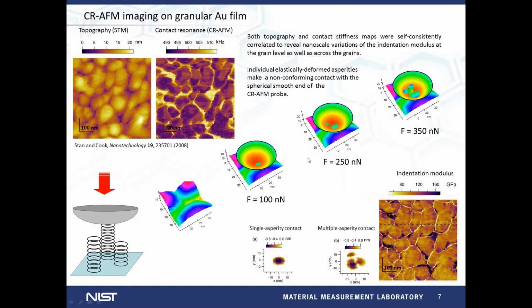An example of more complicated contact geometry is shown here on a granular gold film, and in this case, during scanning, the tip sample contact experienced significant changes in terms of contact area size and number of contacts. The contact is in the form of single asperity contact on top of the grains and in the form of multiple asperity contact in between the grains when the tip comes in contact with the adjacent grains. The way to calculate the elastic modulus map was to, after the contact resonance was made, image the area in STM to get a more accurate topography and combine these two images in the following way. We simulated the tip coming in contact at a given location and pushed into contact until the applied load and the measured contact stiffness were recovered, and at that point observed what the contact area was and then calculated